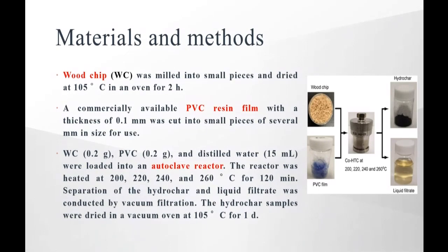The reactor was heated at 200, 220, 240, and 260 degrees C for 120 minutes. Separation of the hydrochar and liquid filtrate was conducted by vacuum filtration. The hydrochar samples were dried in a vacuum oven at 105 degrees C for 1 day.